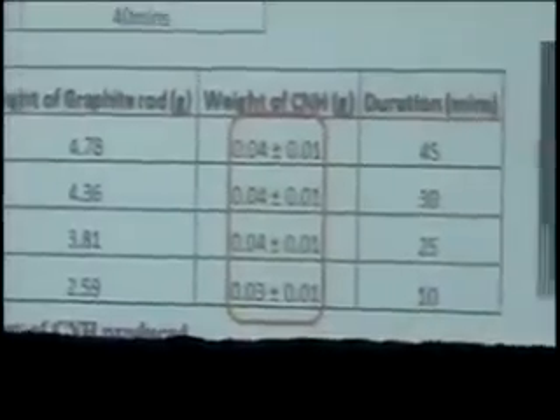Also, when you look at the production rate for carbon nanotubes from 50 to 70, it was very low, like 0.03 grams per hour. However, when the current increased from 80 to 100, there was an increase in the production rate. But this increase too was not substantial as you vary the current from 80, 90 to 100.